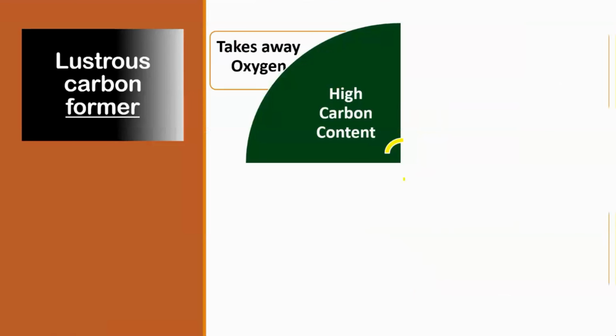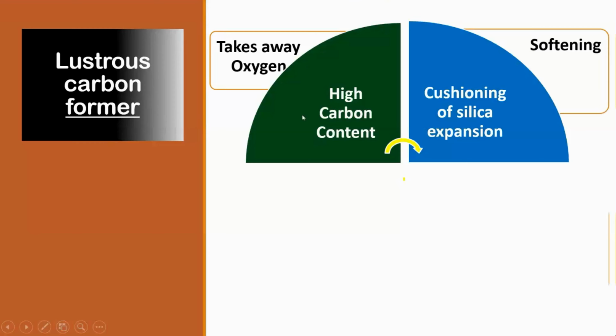So what we need is not lustrous carbon inside the mold, inside the sand. We want what is called lustrous carbon former. Lustrous carbon former is the volatile addition that we are going to do. It has to create lustrous carbon while the metal is poured. So it takes away the oxygen to start with. So it has to have a high carbon content. And then it also gives a softening effect. So it cushions the silica from its expansion.